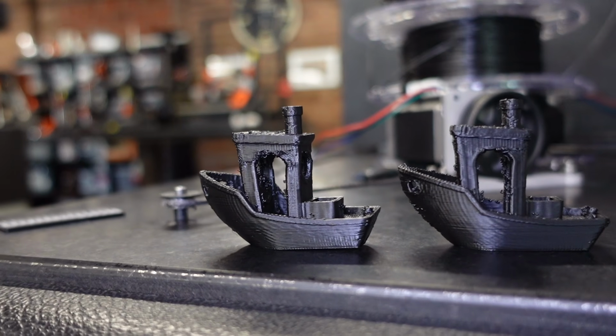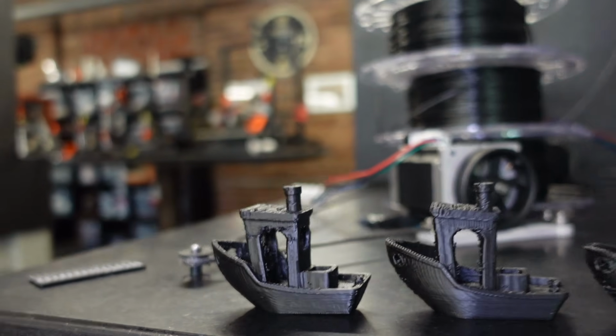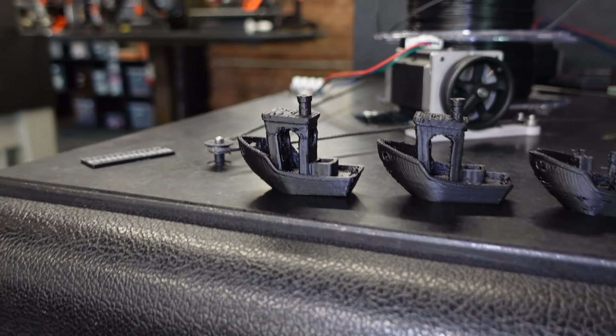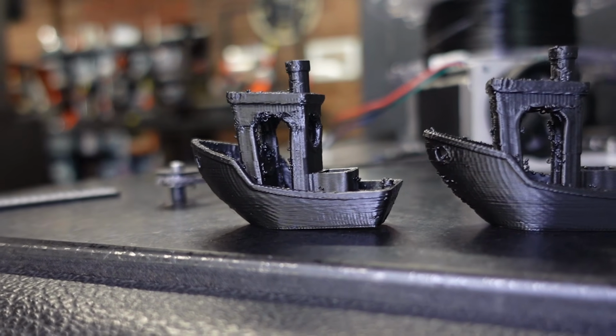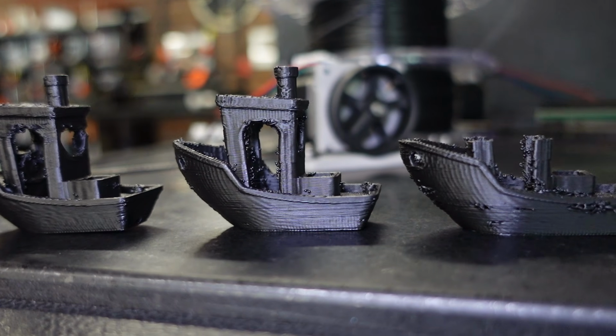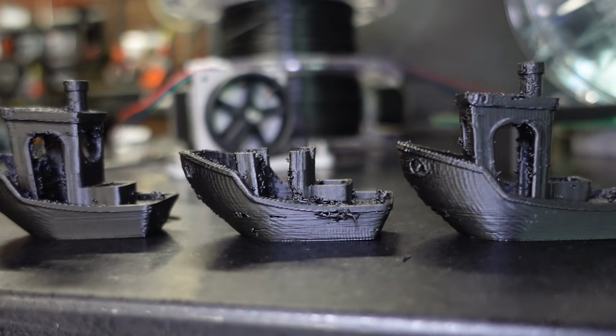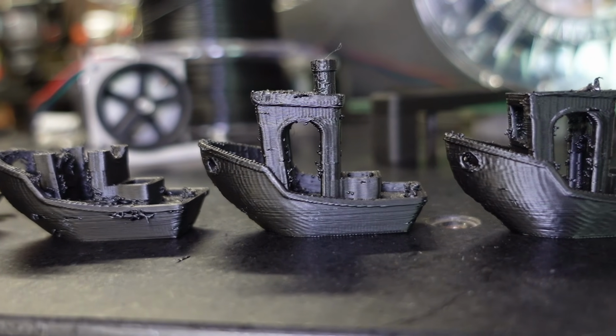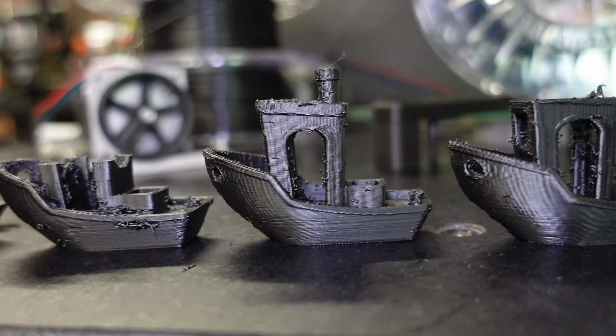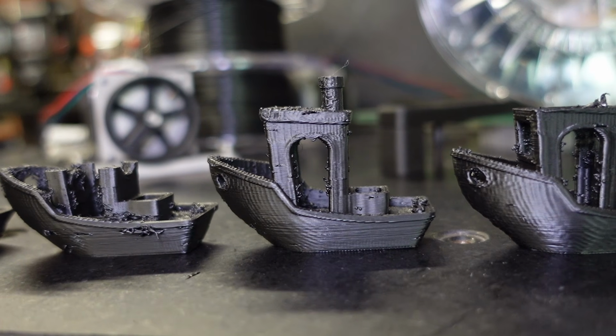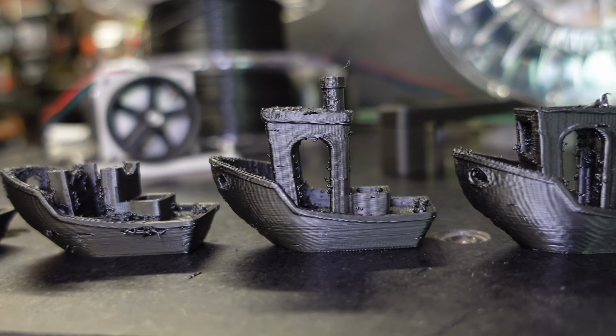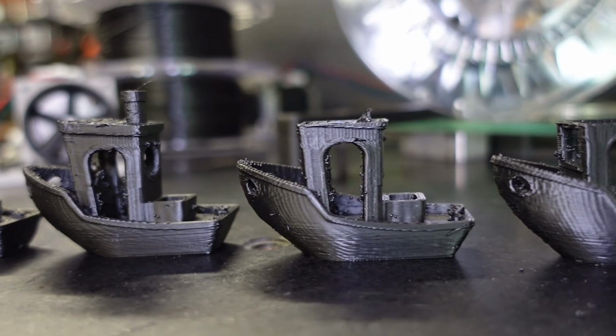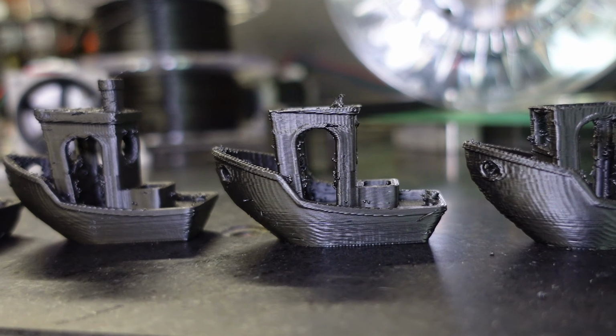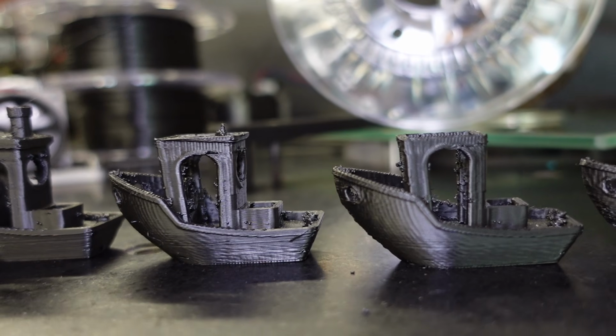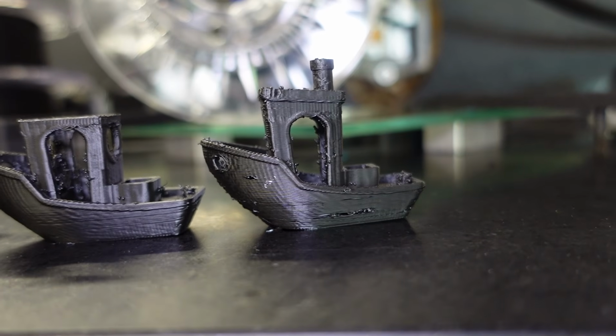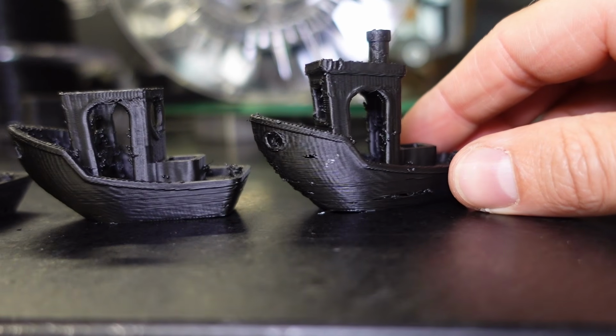So for the very first, we started out basically from here to here. This is half a bar of cooling pressure and 225 degrees. This is also 225. Forget about that. Then I got down to 215 and even did one with 208, but this was too cold. Went back to 215 and cranked up the cooling to 1 bar. Then I had some issues with bad adhesion, and this is kind of my finished product for now.